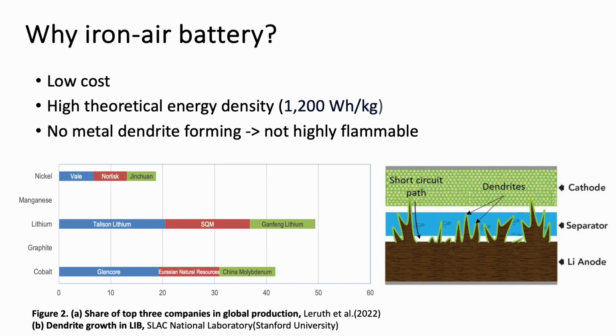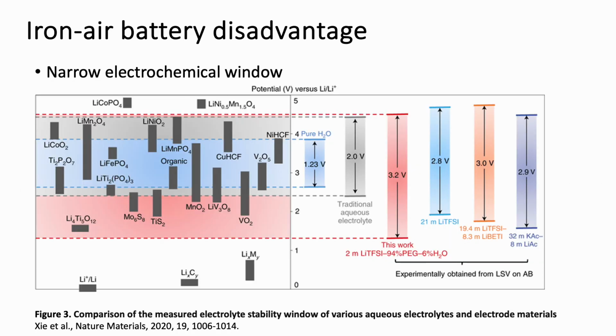These advantages make iron air batteries very suitable for grid storage, but there are some disadvantages as well. First, the electrochemical window of the iron air battery is narrow because of the aqueous electrolyte. The electrochemical window is defined as the gap between the oxidation and reduction potentials. An anode with an electrochemical potential above the electrolyte reduction potential could reduce the electrolyte, and a cathode with an electrochemical potential below the electrolyte oxidation potential could oxidize the electrolyte, and that's not supposed to happen for the battery to work properly. So since iron air batteries use an aqueous electrolyte, which has a narrow electrochemical window, the amount of voltage we could use gets limited.